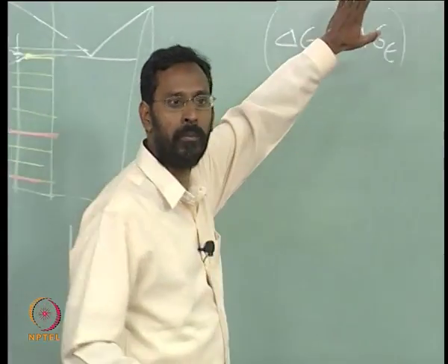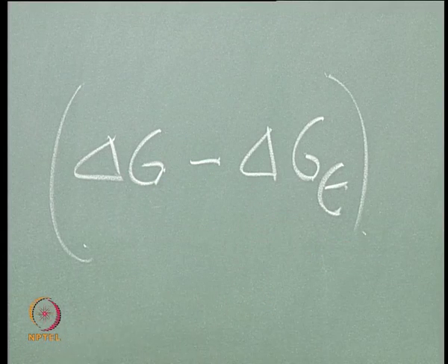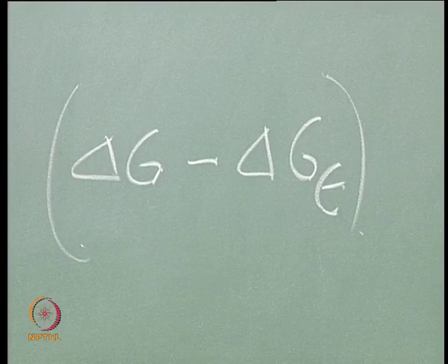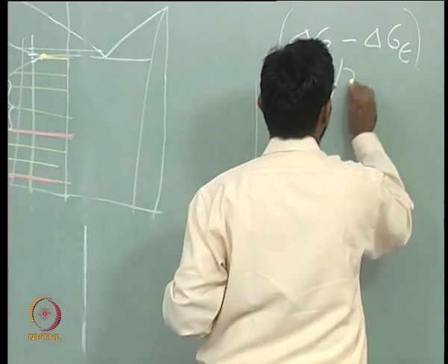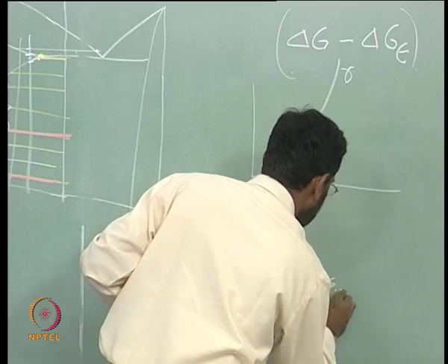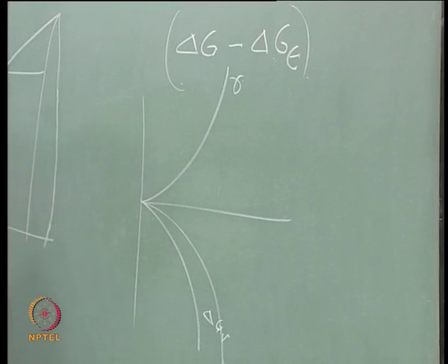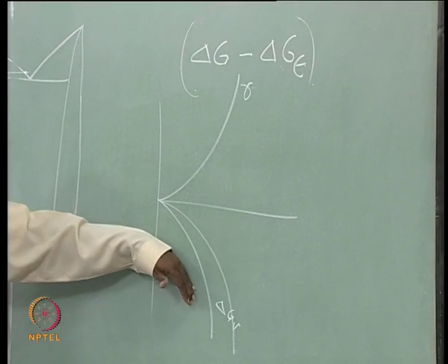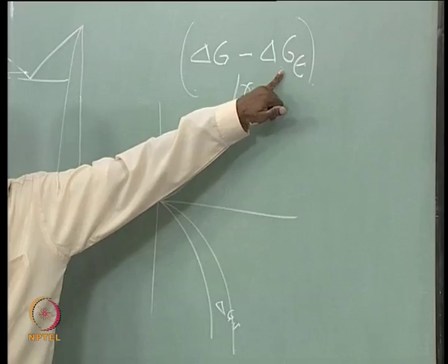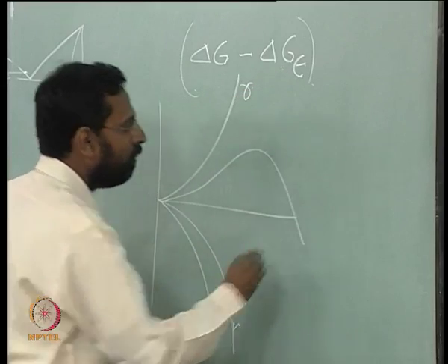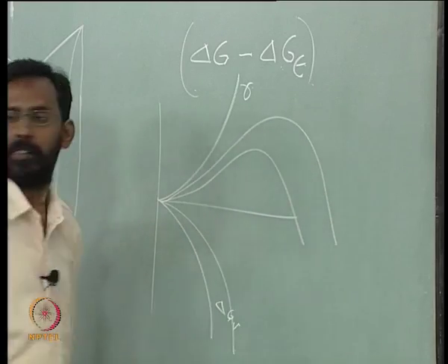Surface energy term is in terms of the per unit area, whereas these two are per unit volume. So, that is why if you look at, for example, a case like you remember this is the gamma term, this is delta G V term. The moment you consider this term will be higher, this is actually negative, and the extent of negative decreases because this is a positive term, and as a result the activation barrier that you are going to get is going to be higher, activation barrier.